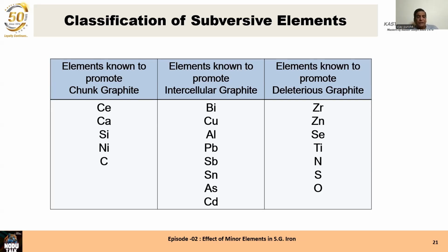First of all, our spectrometers are not having channels to detect these elements. And in some cases where they have the channels, we don't have the standards to calibrate the channels to know at what level these elements are present. Because if we know at what levels these elements are present, we can use cerium to neutralize the effects by adding cerium at least to the same level to which these bad elements are present in the liquid metal. So the deleterious elements are so bad, and their detection is so difficult, and their levels are so difficult to analyze because the standards are not available to calibrate the channels on the spectrometer.